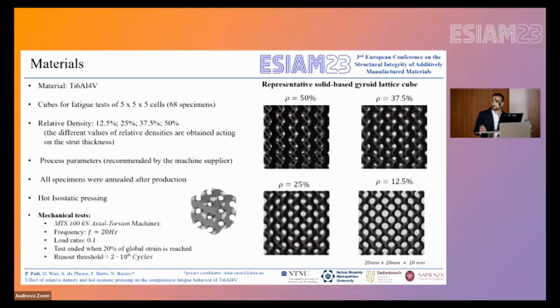The material we chose to investigate is titanium alloy. From this material, we realized cubes for the compressive fatigue tests, composed of 5 cells for each edge. And we chose 4 different relative densities: 12.5, 25, 37.5, and 50%. The cell structure that we have chosen is the solid-based gyroid lattice, and we acted on the strut thickness in order to change the relative density of this structure.